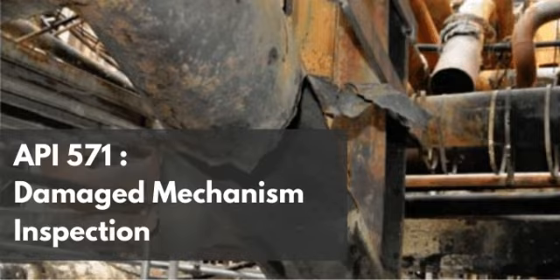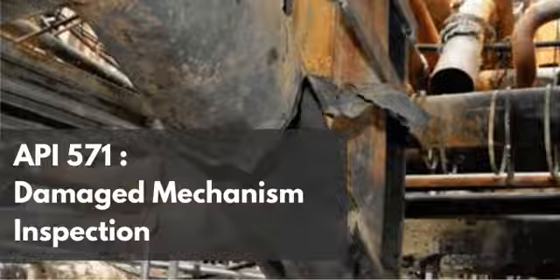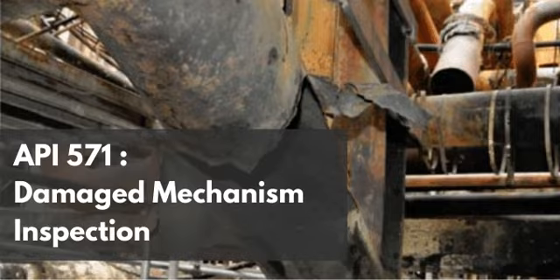So lean amine is dangerous because it's aggressive and the steel is bare. Rich amine is safer because it builds its own protective shield on the steel. Exactly. But, and this is a big but, the text does not give rich amine a total free pass. Right. It explicitly states that rich amine systems are less susceptible, but it outlines critical exceptions. There are specific vulnerability zones, even in the rich amine loop. Yes, and these vulnerability zones exist wherever the thermodynamic equilibrium of the fluid is disrupted. The highest risks in rich systems occur specifically in vessels where the chemical state is actively changing, right? Where the acid gas is either entering the amine or leaving the amine.